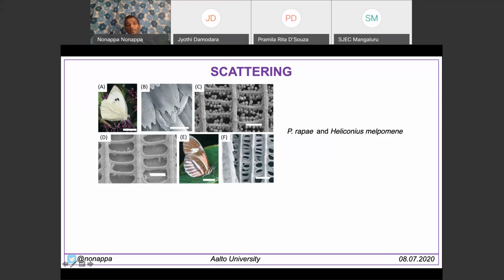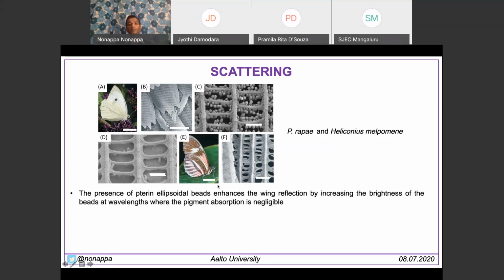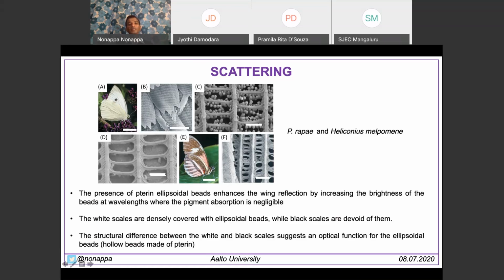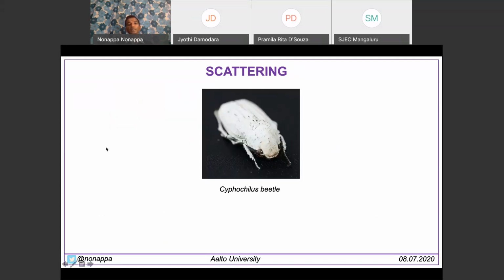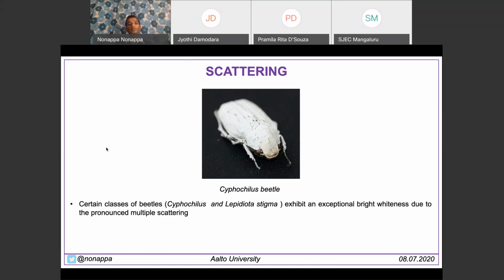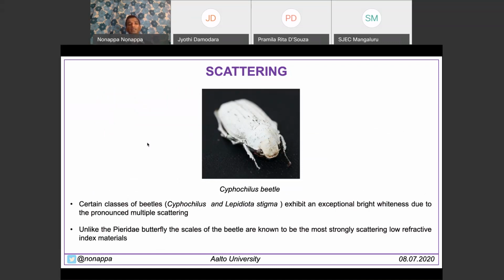And if you take the black patch now, D, which shows the SEM image, it's not colored, it's a black color, and there are no ellipsoidal patches. The same holds true for this particular species. Where it's colored, you take any portion of this, you don't see these ellipsoidal structures. So it eventually has to do with these nanostructures that help you have a very bright coloration. And in this case, it is due to multiple scattering, and it is essentially made up of very low refractive index materials.